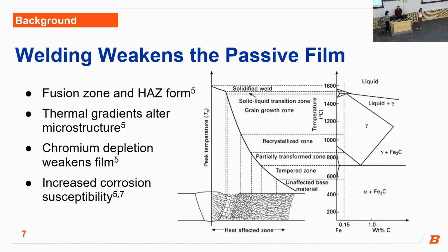As mentioned before, welding also creates a HAZ, the heat affected zone, where the material doesn't necessarily melt and re-solidify, but does get hot enough to change the microstructure. It also introduces a fusion zone, where it's actually melting and re-solidifying. The gist of this phase diagram is that within varied positions of the weld, the material is heating and cooling differently, and this is leading to variation in the microstructure. It can also lead to chromium depletion at the grain boundaries, which can weaken that passive film so it can lose its ability to self-heal.